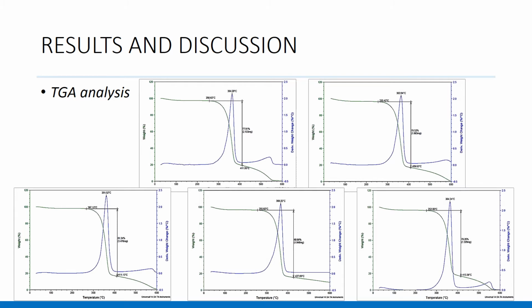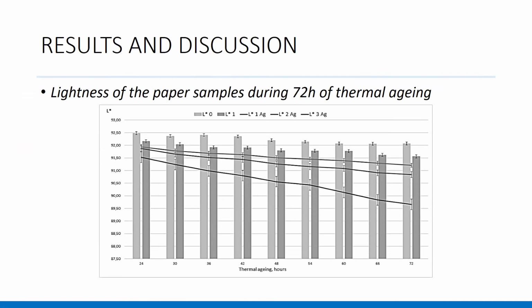The pattern of the thermal destruction of the investigated samples is not different. Undoubtedly, the different behavior of the sample with 3 milliliters of silver water makes an impression, which burns faster and is characterized with weight loss of 25% in the range of 375 degrees Celsius.